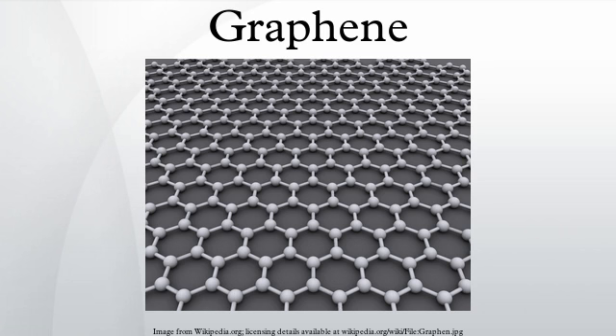First, microcrystalline graphite is treated with an acidic mixture of sulfuric acid and nitric acid. A series of oxidation and exfoliation steps produce small graphene plates with carboxyl groups at their edges. These are converted to acid chloride groups by treatment with thionyl chloride. Next, they are converted to the corresponding graphene amide via treatment with octadecylamine. The resulting material is soluble in tetrahydrofuran, tetrachloromethane and dichloroethane.